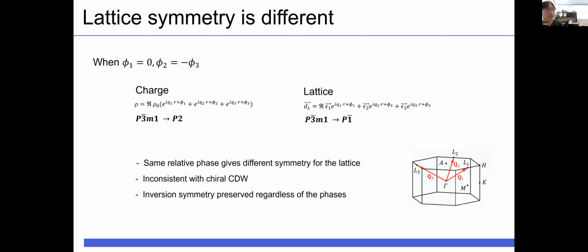Then it cannot break inversion symmetry. Also, any combination of L phonons cannot break inversion symmetry of the lattice. This is a problem because it's contradictory to Neumann's principle, which means that the physical properties of materials must be the same as the symmetry of the lattice. So therefore, another displacement should be considered to break the chiral symmetry in the lattice.